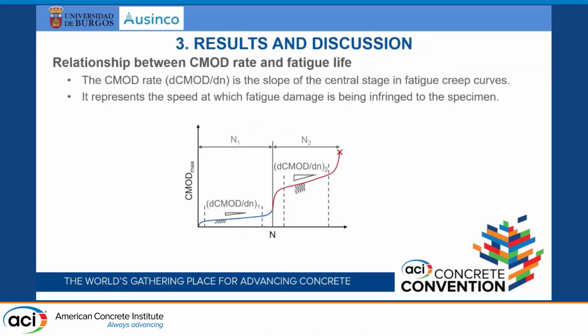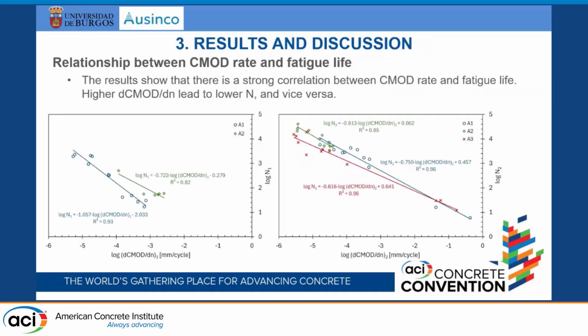Okay, so apart from that, the second objective was to try to find parameters in the fatigue creep curves to predict fatigue life, to try to understand what happened with fatigue life. And there is a very, very important parameter, which is the CMOD rate. The CMOD rate is the slope of the second part of the S curves. In the general case, we have two CMOD rates, the one corresponding to the matrix fatigue and the other one corresponding to the fiber-matrix bond fatigue. So we can extract this parameter and correlate each CMOD rate with the corresponding fatigue life. And here we have the plot in logarithmic scale.